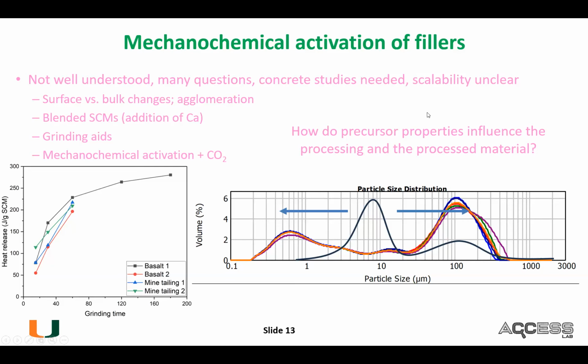And we actually get some very interesting effects. I call this parting the Red Sea. In many cases, we have an original particle size distribution that looks something like this. After mechanochemical activation, we get a bunch of very fine particles, but then we get a bunch of very, very, very coarse particles as well. This is interesting because presumably that right side is agglomeration. And we've tried a bunch of things, but it doesn't seem to really go away.